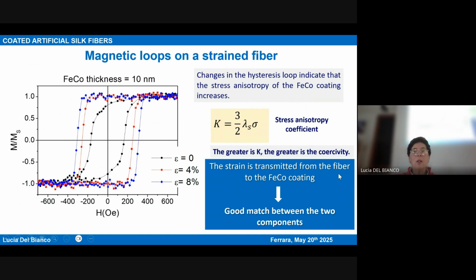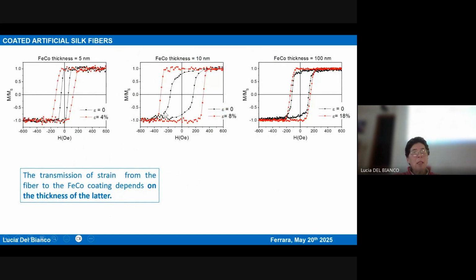and because it demonstrates that indeed the strain is transmitted from the fiber to the iron cobalt coating, and this means that there is a very good match between the two components. So the two components, although they are so different from the mechanical point of view, are well coupled. And this transmission actually depends on the thickness of the iron cobalt coating. And therefore here I show you three different types of fiber. I compare the hysteresis loop measured at zero strain and in the strained fiber.